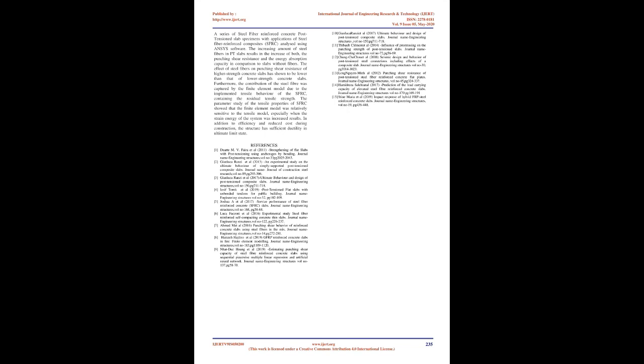The effect of steel fibers on punching shear resistance of higher strength concrete slabs has been shown to be lower than that of lower strength concrete slabs. Furthermore, the contribution of the steel fiber was captured by the finite element model due to the implemented tensile behavior of the SFRC, containing the residual tensile strength.